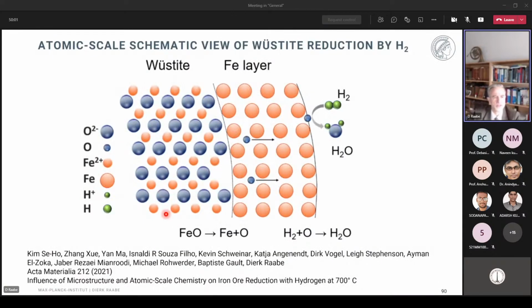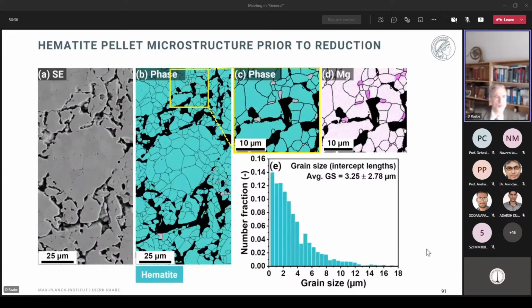When you cast this into a schematic picture like shown here, you can see that the real bottleneck is that you must bring the oxygen ions through that firstly formed iron layer, which is here plotted pretty dense, so that on the next nearest surface the water as a reaction product can form. So you have these kinetic and thermodynamic settings that show that once an iron layer which is dense has formed, this process is indeed a bottleneck process, gets very slow. Now let's look into a real pellet.